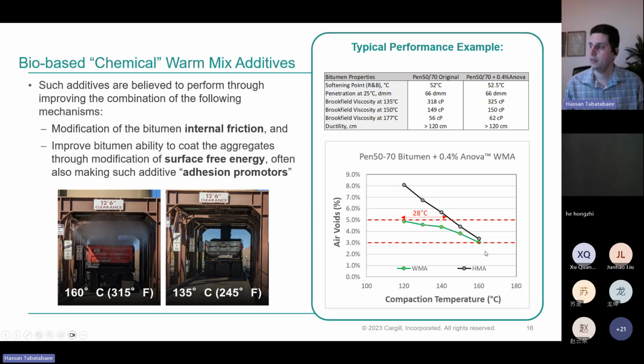However, when you look at compaction, here's an example of two mixes, one with a chemical bio-based warm mix additive, and one without. As expected with the normal asphalt, as you drop the production temperature, the air voids achieved at a fixed compaction effort continue to increase. However, when you use a chemical warm mix additive, although you do still see an increase in air void as you drop the temperature, that increase is a lot less. And you can see in certain points, there's a significant shift in the compactability temperature. You're achieving similar air voids with the warm mix at 20 to 30 degrees lower temperatures than you would with the hot mix alternative. And that means lower fuel use and lower carbon footprint.